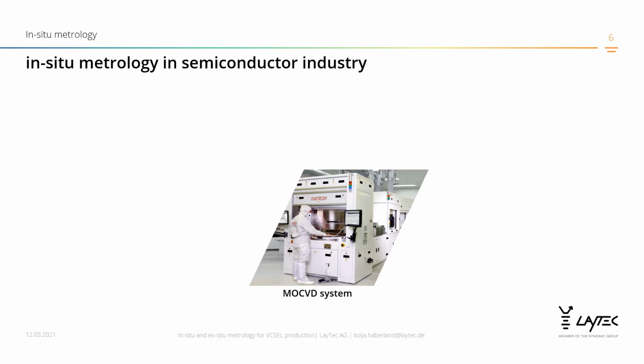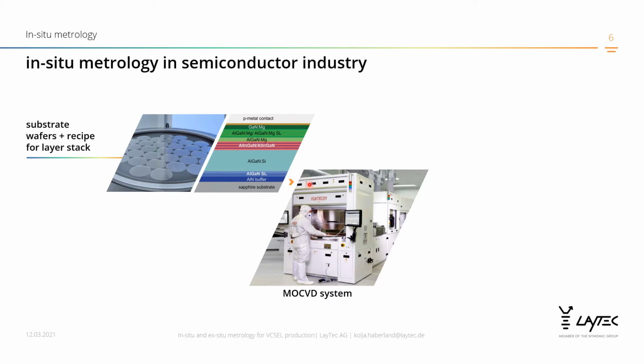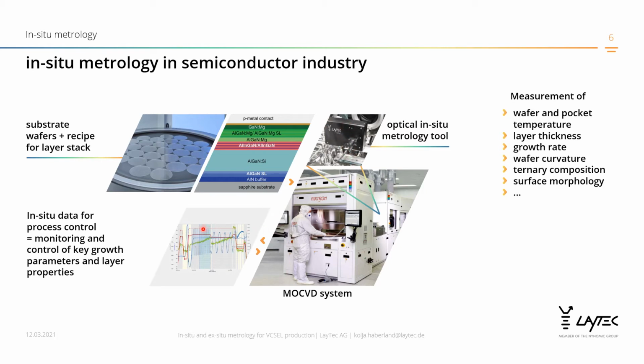Let me now show you in more detail how the in-situ metrology works. Here in the center we see the MOCVD system where the layer stack is grown. Wafers are loaded and the layer stack is provided as a recipe. Inside the MOCVD system, our LayTec metrology system is installed on the reactor lid, looking at the wafers during the process and providing a lot of useful data in real time that are interfaced with the growth system so that closed loop control is possible.